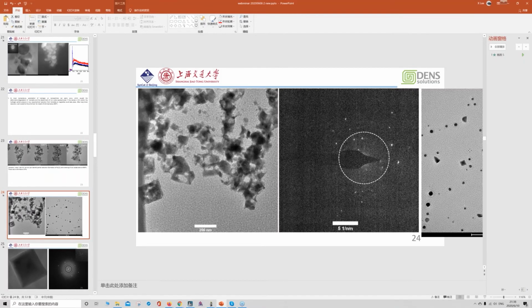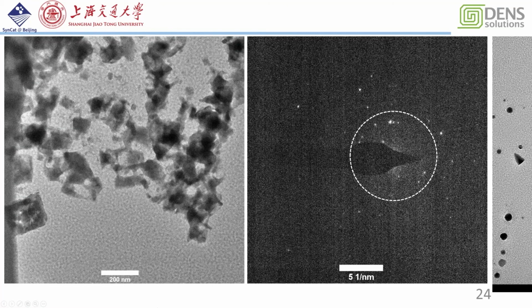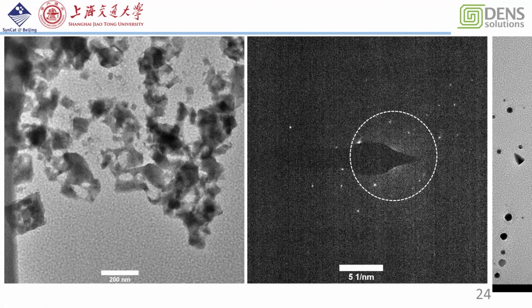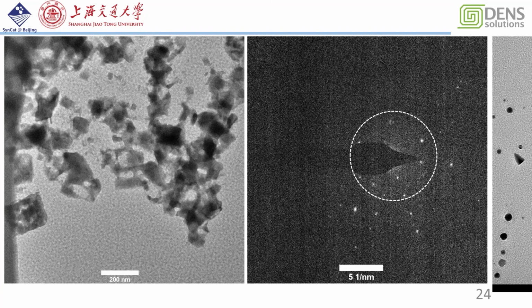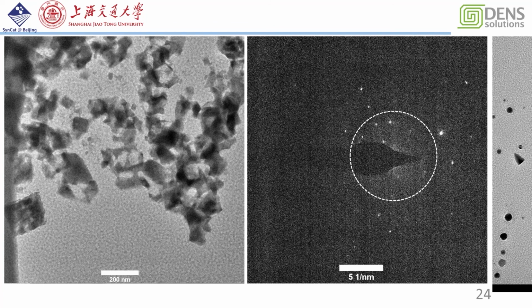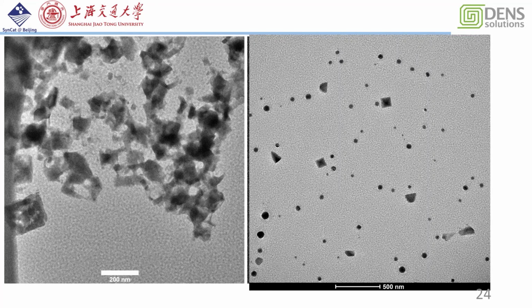So we used both the in-situ TEM and the in-situ electron diffraction technique to examine how the reduction happened below 800 degrees. We can see the particles suffering the strong reconstruction process and the growth of the new crystallines, the magnetite particles with a very beautiful particle shape. But during the whole reduction process, the iron didn't form below 800 degrees. And this is the final picture we got below 800 degrees. So we see that we got the octahedral shaped magnetite particle, but no iron formed.